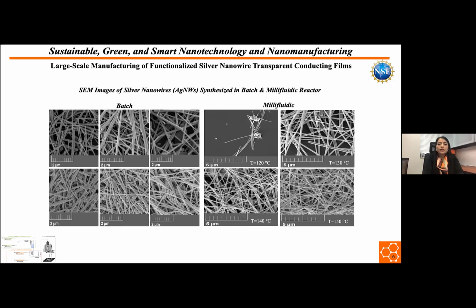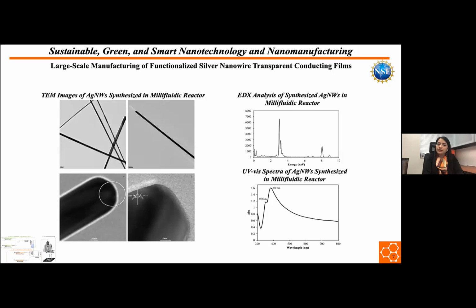And here you can see some TEM images of very long, thin nanowires, which means that we are producing high aspect ratio silver nanowires in a millifluidic reactor, which is really important for us to create transparent conductive films. Also, our elemental, or EDX, analysis shows that these one-dimensional nanostructures, or nanowires, consist only of silver, and our UV spectra of silver nanowires produced in the millifluidic reactor show that we don't have any other nanostructures.